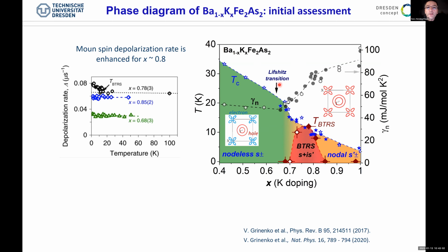One has to say the Lifshitz transition appears at different dopings for different situations in the C direction, because there's warping of the Fermi surface in C axis. So this is certainly broadened, and one can see this, for example, in the normal state Sommerfeld coefficient. There is no real peak here, like what you would expect at a Lifshitz transition. It simply starts to increase here.